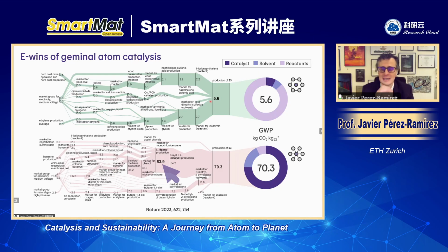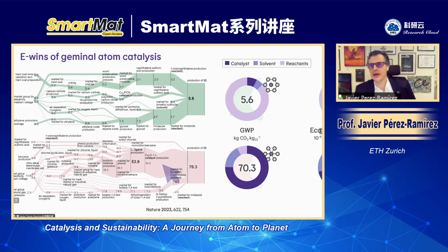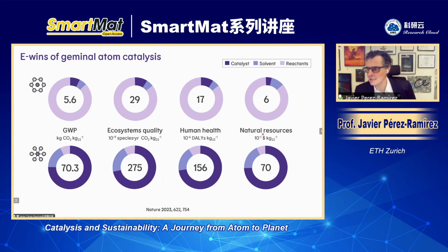In our case, with geminal atom catalyst, we don't have that burden because our ligand is actually polymeric carbon nitride. Our ligand is a solid that is extremely cheap. And that's why we can produce not only amazing reactivity, but also, in my opinion, excellent benefits for the environment, shifting from homogeneous catalyst to geminal atom solid catalyst. These benefits for the environment are not only in the carbon footprint of the product, but in many other indicators that are commonly used in life cycle analysis, like the ecosystem's quality. We also decrease the impact 1 order of magnitude. Human health, we decrease the impact of the technology by 1 order of magnitude, and as well as in the use of natural resources. So processes catalyzed by geminal atom catalysts respect the environment much more.